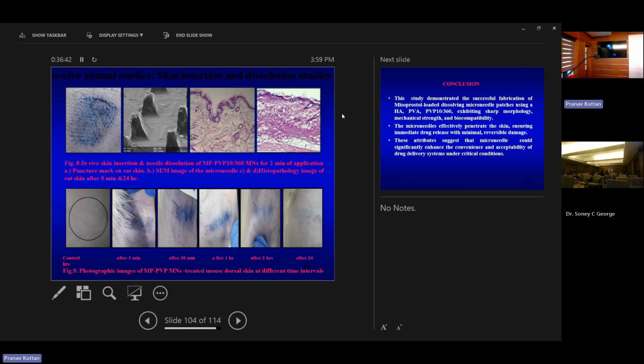Then this is the microneedle. After application, we took it out, lyophilized it and analyzed using SEM. So we can see that the thick portion is gone. That means it has dissolved within 2 minutes itself. And that skin portion, we gave it for histopathology and we could see insertions. After 24 hours, we can see that these are resealed. Whatever is formed is resealed. We also saw the irritation: within 5 minutes there are pores, 30 minutes also it is there. But within 24 hours, whatever pores are formed are resealing. You can see it here. And it is creating no skin irritation.